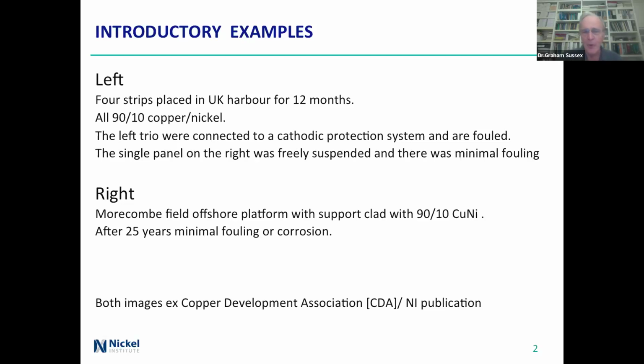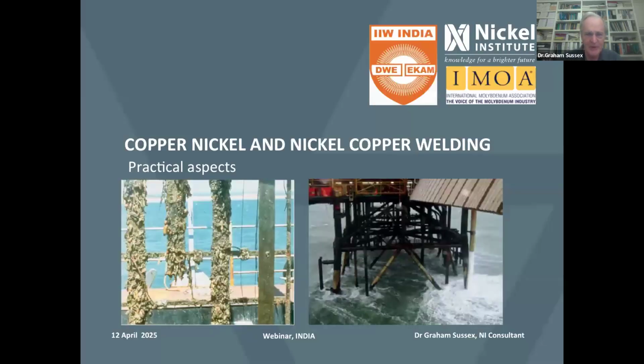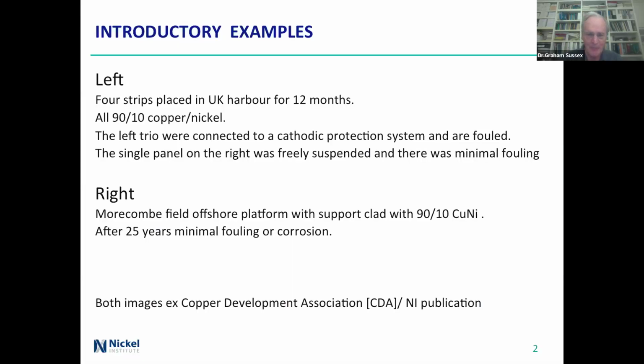The single panel on the right, freely suspended, not connected to the cathodic protection system, had minimal fouling. So they're all the same material - the 3 on the left were cathodically protected, the other one wasn't, but it's the copper dissolving which actually gave you enough protection to stop the bugs landing.